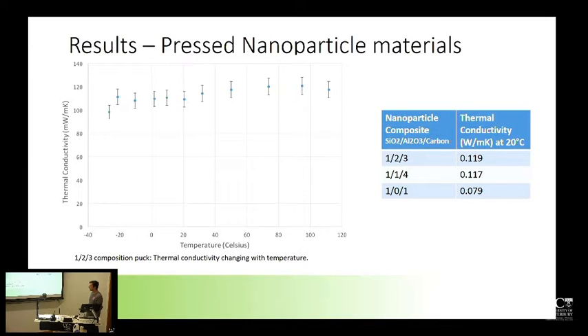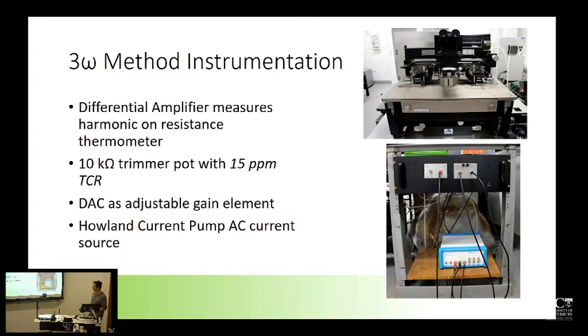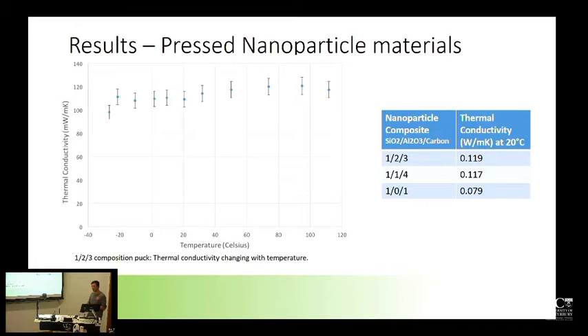I wonder whether that test methodology is unsuitable for the material, given that carbon is sort of a radiation suppressor. It is absolutely lamp black when you look at it. And I wonder if there is some reason that they weren't getting any signal out the other side of that laser flash calorimeter. Because they made a larger tile and measured that with a guarded heat calorimeter, the same that Callaghan Innovation measured it with, and they got a value which was almost exactly what I'm measuring here. So I wonder whether their numbers are correct on that or not.